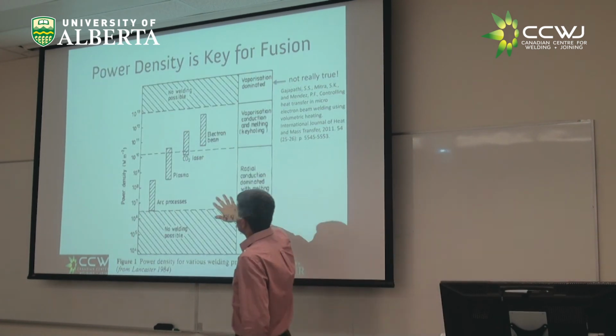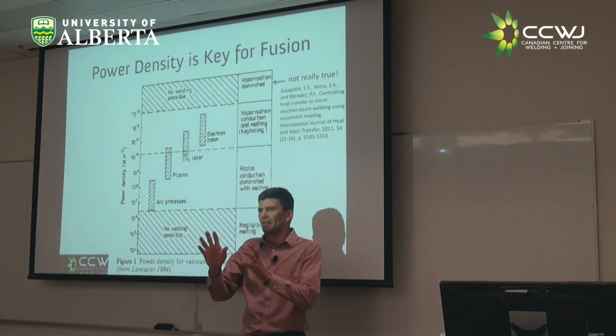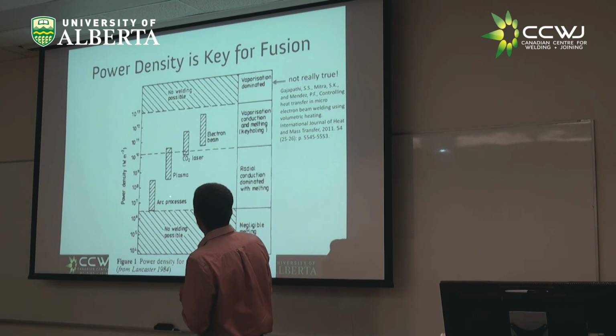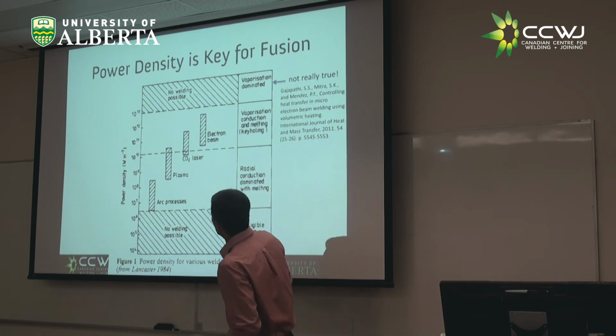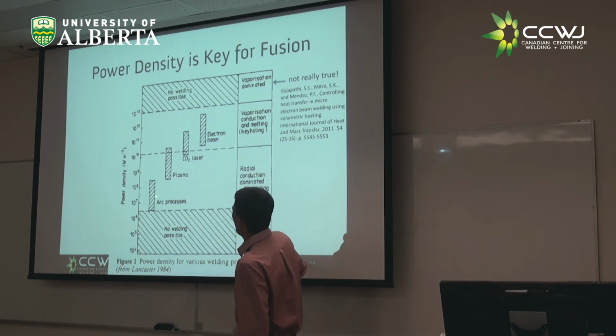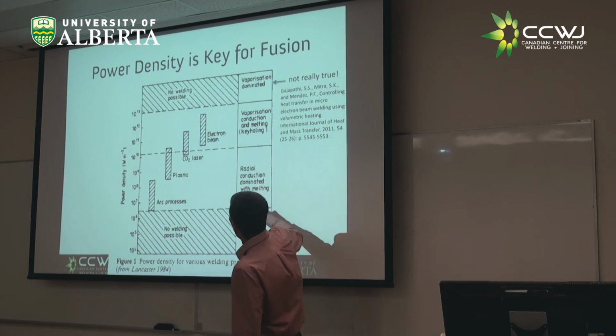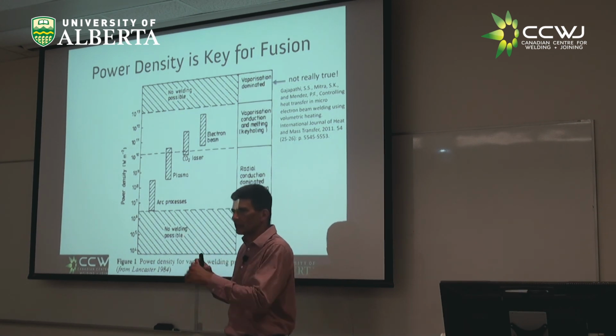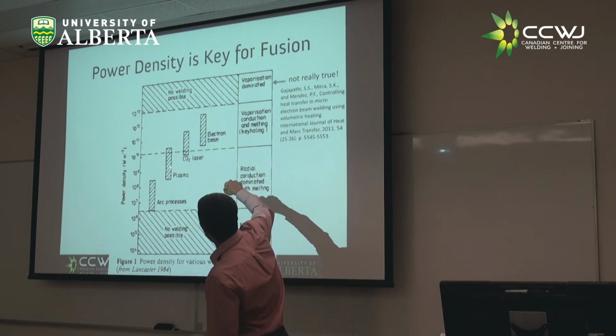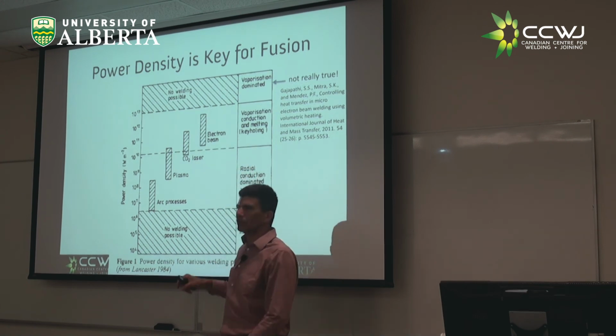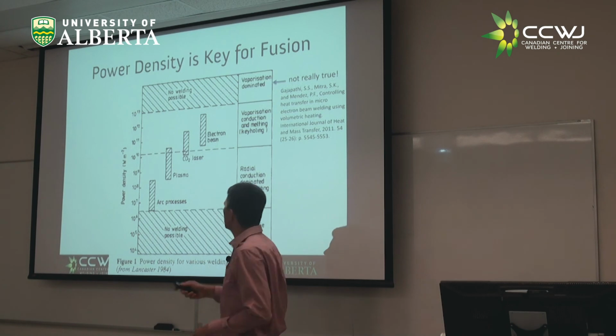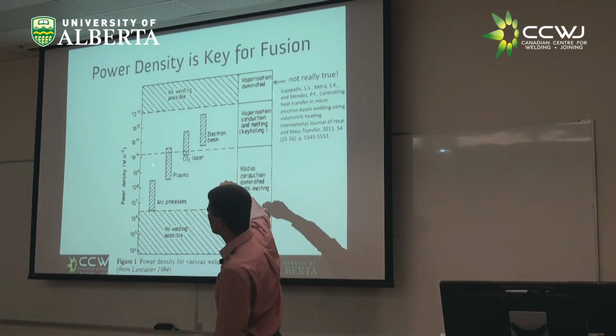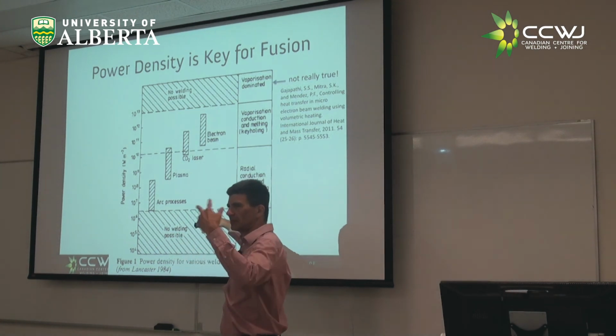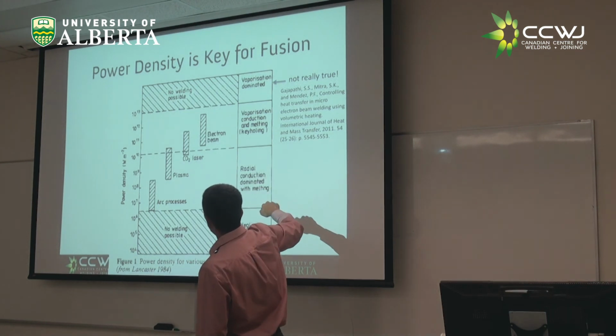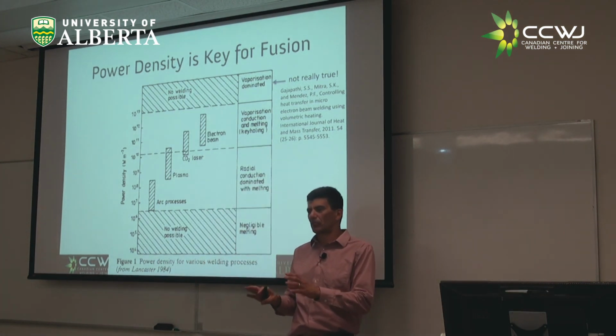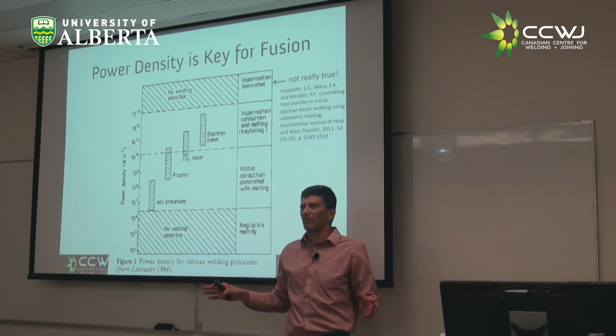So you can make this graph that says the power density is related with the type of energy you have. And this power density gives you many things. Arc processes have a power density of about 10 to the 7, 10 to the 8 watts per meter square. Plasma is more or less the same, but with some constraints which we'll discuss next week, a little higher energy density. Lasers or electron beams are called high power, high density heat sources. Higher. This is log scale. So each notch means 10 times more intense. What this graph also says is that if you have a heat source that is not intense enough, you don't melt anything. And it's true.